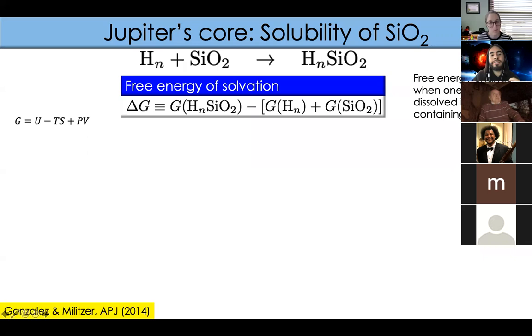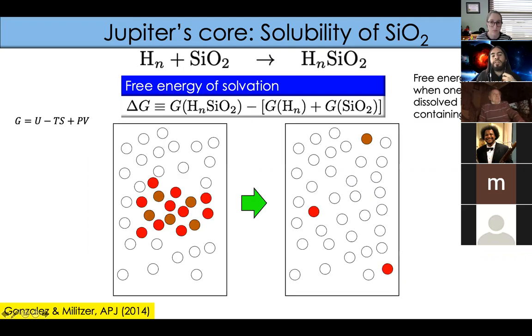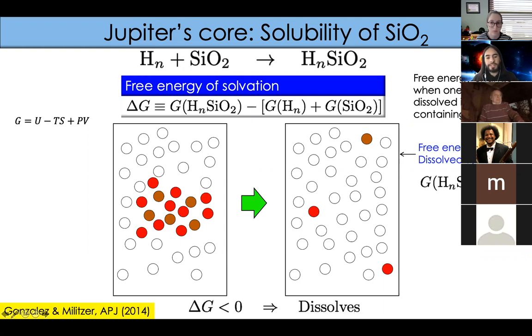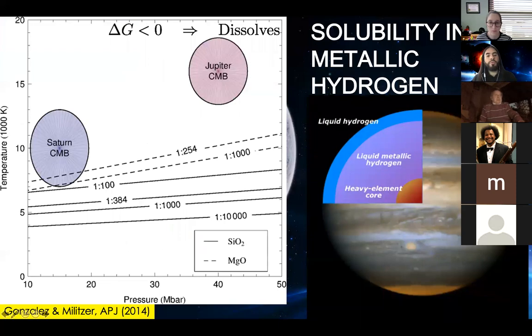And the way we do it is calculating the Gibbs free energy of solvation, which is basically trying to see whether the Gibbs free energy of the dissolved state here is smaller than the Gibbs free energy of the state that is not dissolved. So it's an energy balance argument. So if this term delta G is less than 0, then the system will dissolve at the pressure and temperatures where we explore it. So that is what we did, and this is what we obtained.